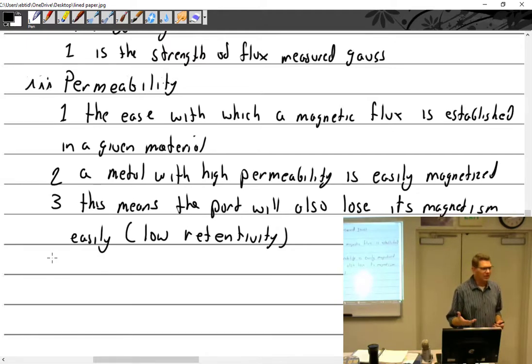Okay. So I've explained to you, and we'll get into this a little bit more, but there's this difference between doing wet continuous and residual. So wet continuous, you have to put the media on the part, and as it's flowing, this residual flow, if you will, because you're not supposed to hold the nozzle on while you're doing it. So you immediately stop the nozzle and apply the current to the part, right? So at that point, you've done a wet continuous, and you would inspect the part. Now, wet continuous has the most sensitivity.